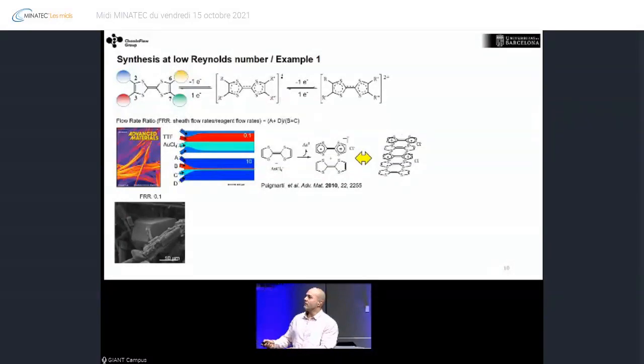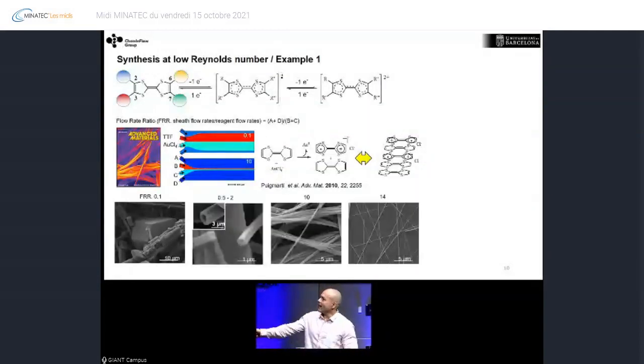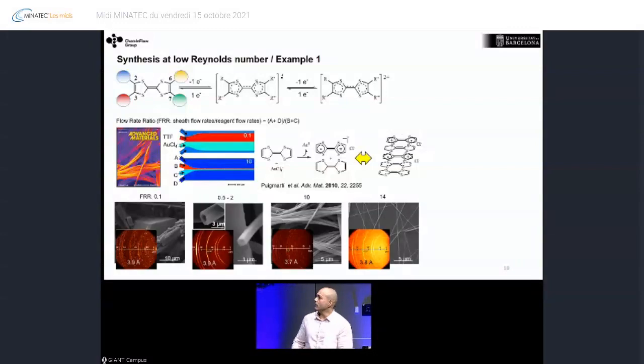So if we do the reaction with microfluidics at very low flow rate ratios, so in this condition here, what we have is a mixture of crystals. This is what you see there. So there is no defined morphology. But look what happens when we increase the flow rate ratio. We are changing the morphology of the material. But not only that, if we do diffraction, what we also change is the pi-pi stacking distance of these TTF molecules in the final structure.